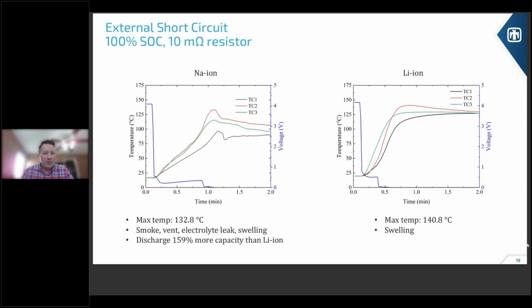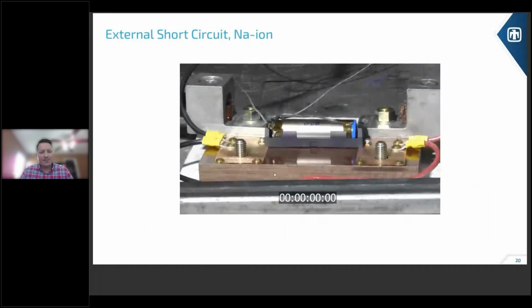So we're moving on to a different type of test. This is an external short circuit. So we have the cell fixed to a circuit that we close, and when we close it, it allows the cell to dump all of its energy almost immediately. The lithium ion and the sodium ion both got to about similar temperatures, around 140 degrees C. The lithium ion only swelled, but the sodium ion actually smoked, vented, and had electrolyte leaking out. And it discharged 159% more capacity than the lithium ion. So next we have another video. You can go ahead and play that one.